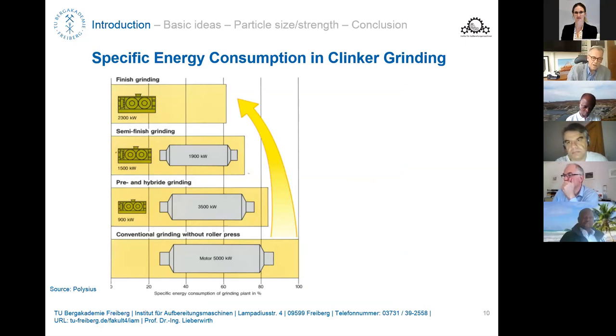So one of the advantages of the confined bed comminution is the reduction in specific energy consumption. This is a picture which was published in a brochure on comminution for clinker grinding. It shows quite nicely the advantages in energy consumption of replacing the then dominant ball mills by HPGR. You can see that at that time a typical ball mill in the cement industry was driven with a 5,000 kilowatt motor. If you would replace it, at least in a hybrid grinding, so-called hybrid grinding or semi-finished grinding, you could